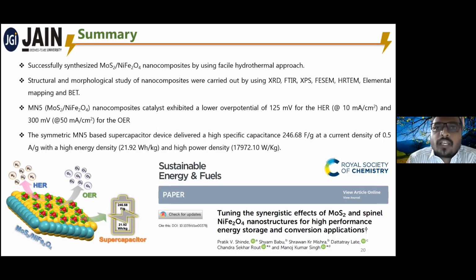Mostly, more active sites increase the diffusion of the electrolyte ions, which facilitates fast charge transfer and enhances the electrochemical properties of these materials.